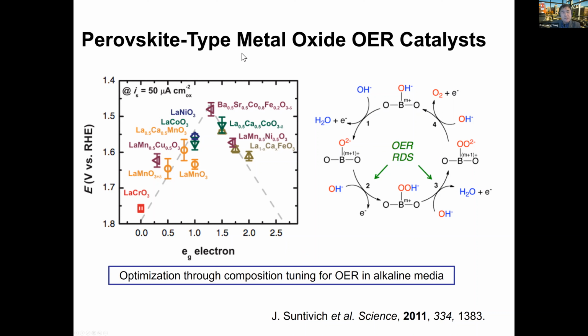the pyrochlore, the perovskite metal oxide OER catalyst being reported by the MIT group that demonstrated you can have a lanthanide-based different kind of composition and lead to a very different performance. And so this is tested at fairly low current densities, but shows a very nice trend that gives you a different kind of overpotential. For example, if you're dialing, let's say, cobalt changed to manganese, or you can choose B sites also changed to different metals, you have the property changes as well.